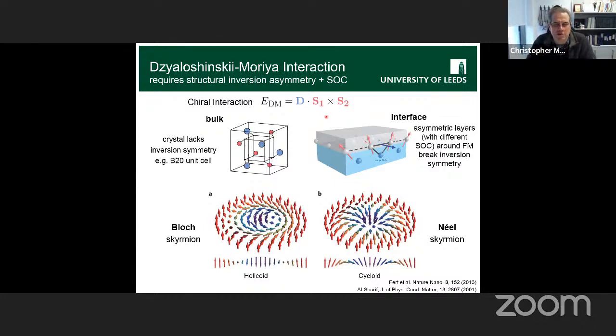And there are two ways that this can happen. You can either get a helical twist or a cycloidal twist. In these interfaces, you generally get this cycloidal one. So these look like Néel domain walls. These look like Bloch domain walls. And if you create a Skyrmion by twisting one of these domain walls into a loop, then you can get these Bloch or Néel Skyrmions. So for pretty much the rest of the talk, we're going to be looking at these Néel type ones.